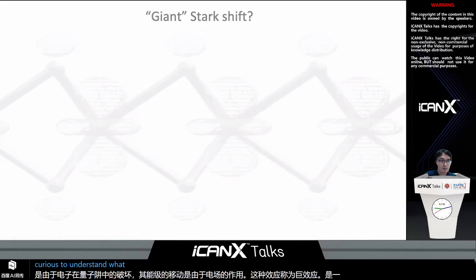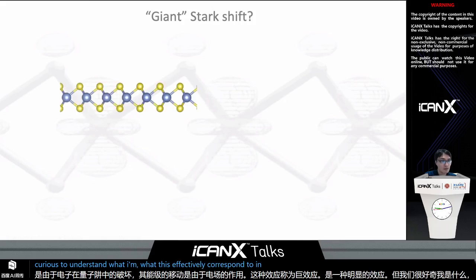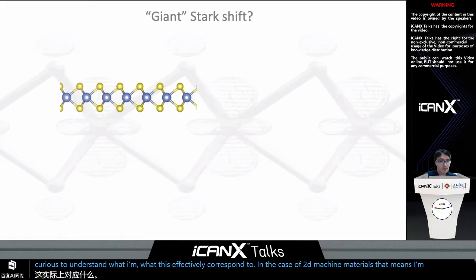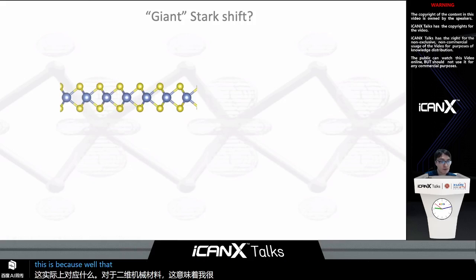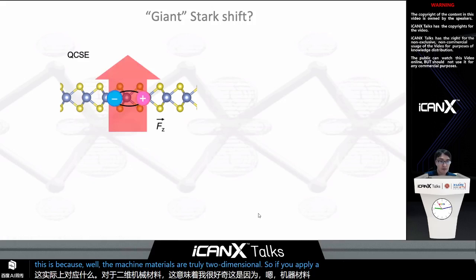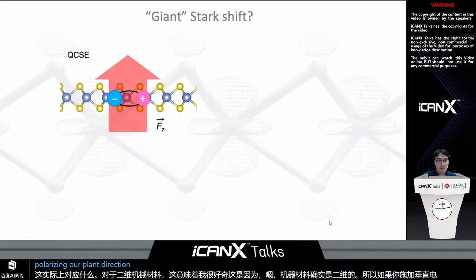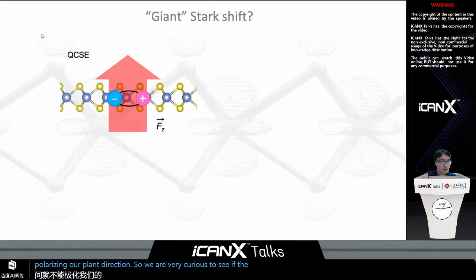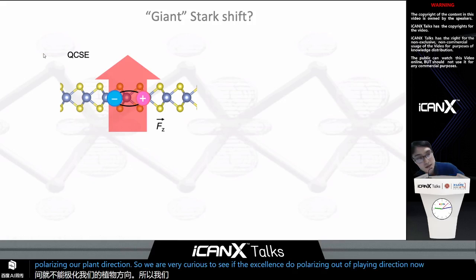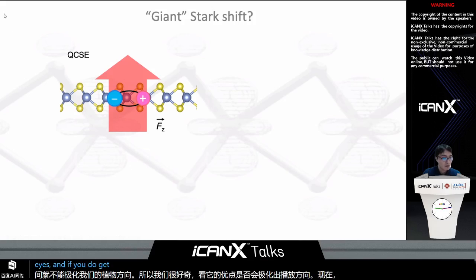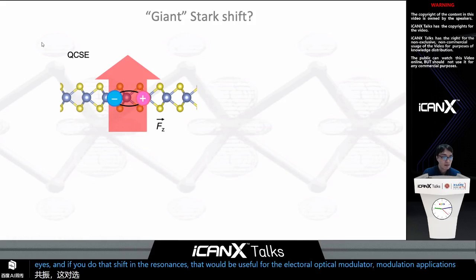Now, this effect is called the giant Stark effect, but we were curious to understand what this effect will correspond to in the case of two-dimensional materials. The reason we were curious about this is because the two-dimensional materials are truly two-dimensional. So if you apply a vertical electric field, the excitons cannot polarize in the out-of-plane direction. So we were very curious to see if the excitons do polarize in the out-of-plane direction. If it does polarize, and if you do get a shift in the resonances, that will be useful for electro-optical modulation applications.